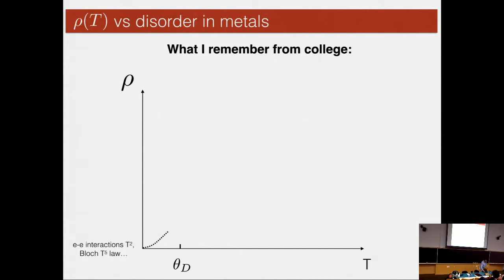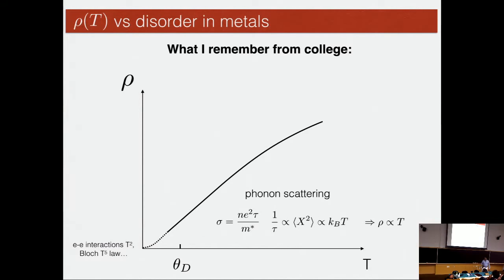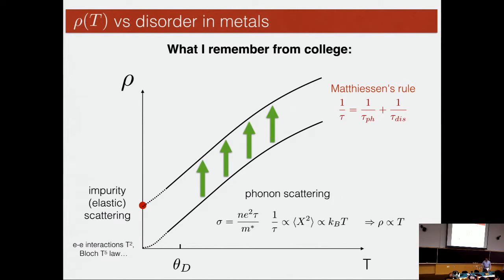But you know, the first thing that you remember from college, so to speak: what happens when you start putting weak disorder in metals? Well, in metals you have phonons. And most of the temperature dependence is linear around room temperature, and comes from scattering of these phonons. When you put in weak disorder, at zero temperature the resistivity becomes finite, and the conductivity also is finite. And then there is this so-called Matthiessen's rule that says that when the scattering events are weak, of any kind, they simply add up, either you scatter off one or the other.